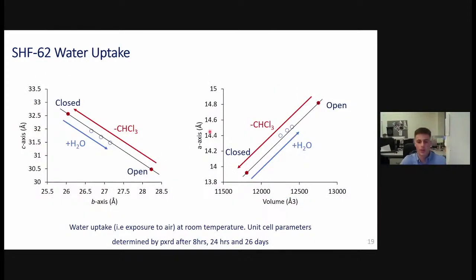So we're also able to demonstrate that this ligand flip is reversible. So this is from data from a powder diffraction study this time. So we start off with our open framework. We can remove the chloroform again by heating. And as before, if we just expose that closed framework to the atmosphere, you see that the framework will gradually reopen. So this last data point was taken after 26 days of exposure to the air. So we see that there's the potential that the framework can fully open, but it goes through that ligand flip.